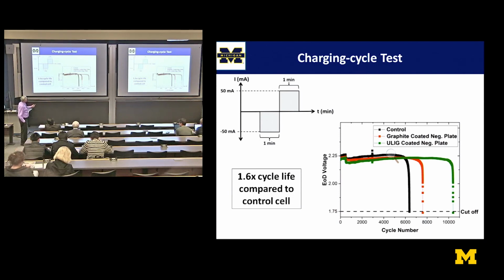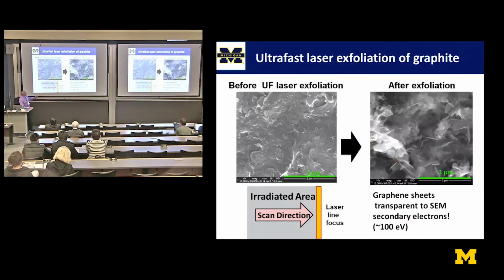just by taking graphite, exposing it to a laser after it's deposited on the battery electrode, and allowing the battery to have a much greater lifetime. Many, many more cycles is one of the limitations of battery technology. You can't cycle them as many times as you would like. This extends the lifetime by a factor of 1.6. And it can be done quite simply, just scanning a laser line focus across a graphite-coated electrode, producing graphene sheets.